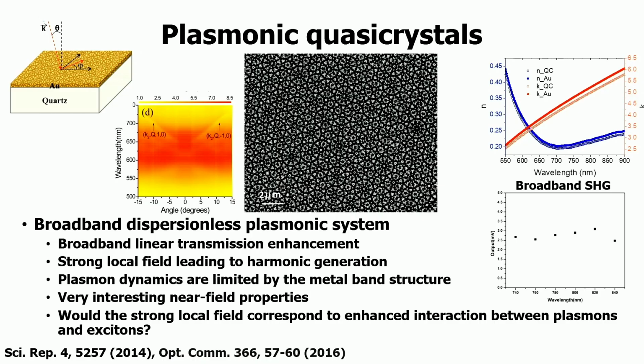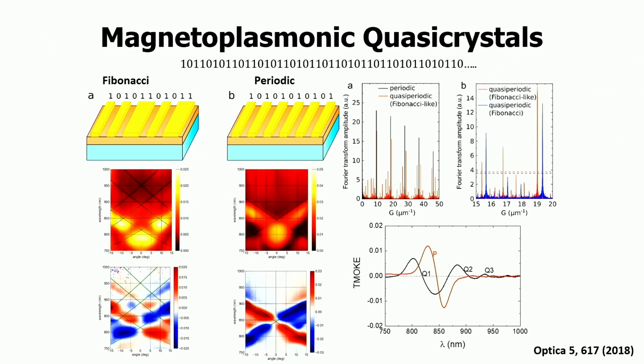orders of magnitude. The local electric field enhancement leads to broadband second harmonic generation because it's a thin film nonlinearity. We are no longer dependent on the phase matching condition here. So just launch at any angle, and you can generate the second harmonic. Of course, the conversion efficiencies are not very high, but you can use this for SHG locally, right? We also showed other interesting properties from these.